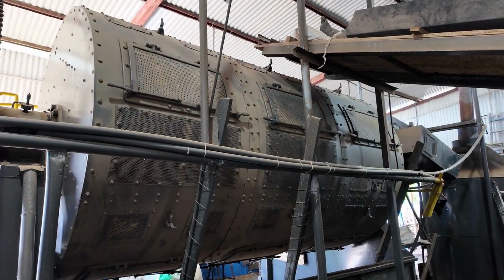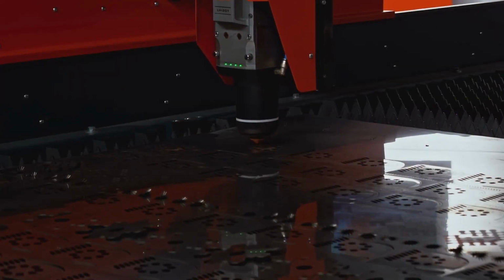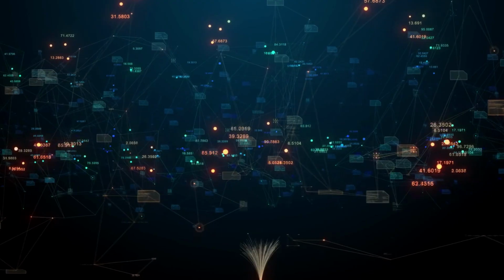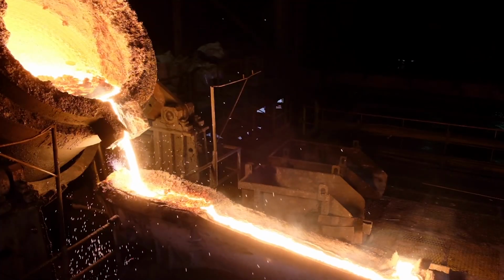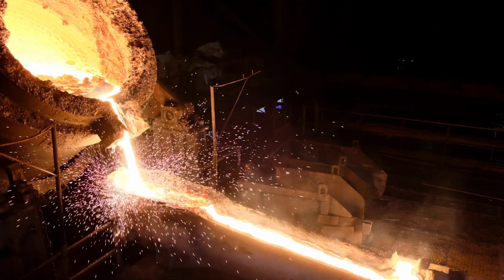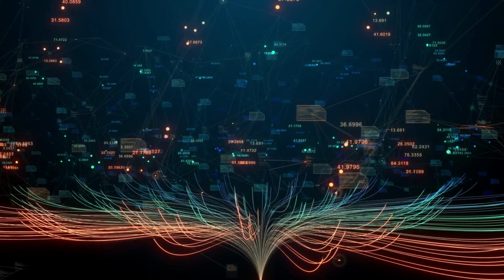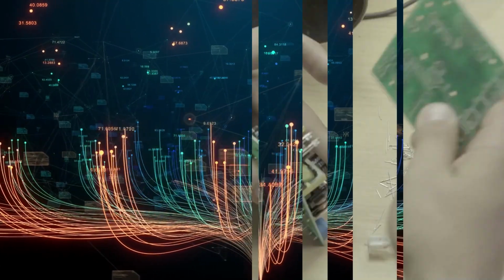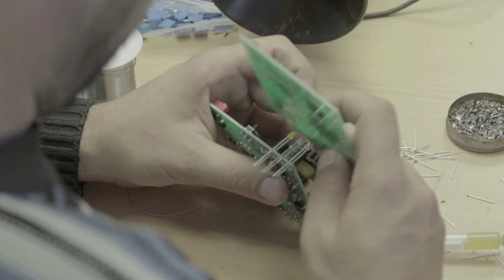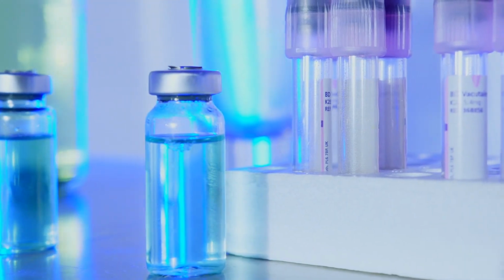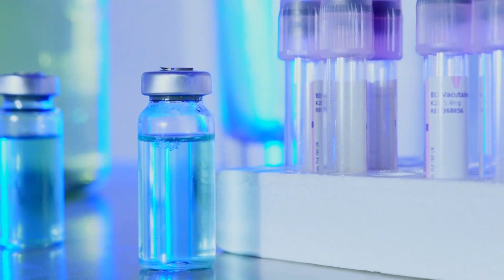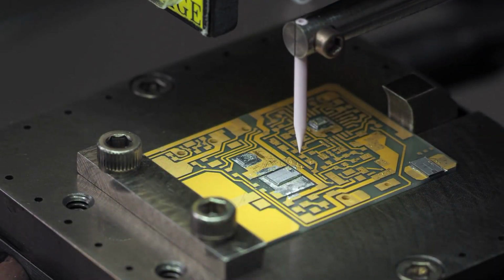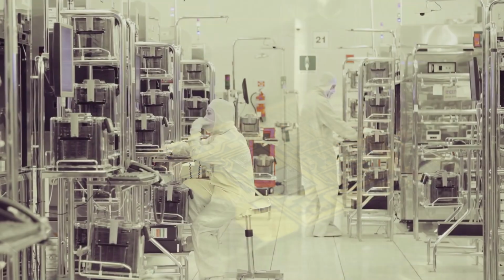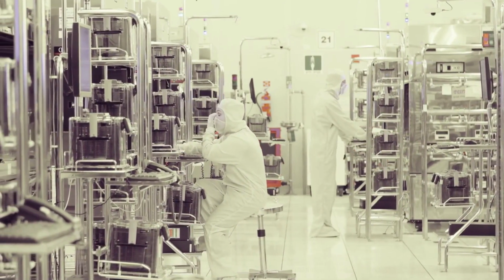But the tool is only half the story. What goes inside the tool, the metal disc the plasma bombards, is where the supply chain becomes genuinely surprising. China produces approximately 40% of global refined copper. By raw metal supply, it is already a dominant node in the global copper chain. But the deposition target is not simply refined copper. It is copper refined to 6N purity, consistently, batch after batch, with metrology precise enough to certify each disc before it enters a vacuum chamber.